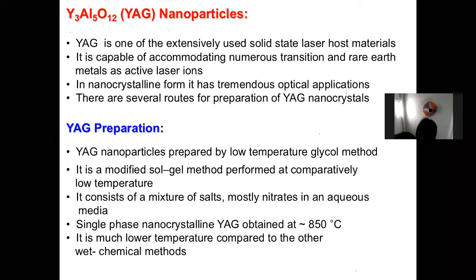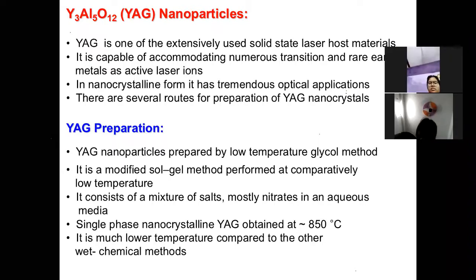But making nanoparticles of that and then making composites with PMMA is very easy and very inexpensive, while making a single crystal is very difficult. It takes a week to grow one crystal, and the temperature is very high. The machine you require, the puller, is of the order of 5 to 6 crore rupees. But nowadays we make nanoparticles of that by the glycol method, which is a very low temperature method, around 800 degrees Celsius.